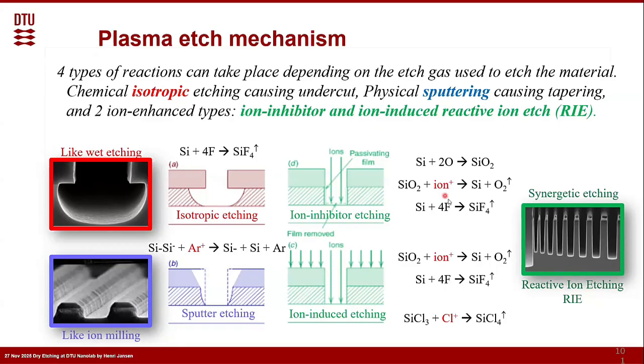And then the 2 most important ones, that is ion inhibitor and ion induced. Ion inhibitor is, in a way, still depending on the isotropic etching, in the sense that the material you want to etch is still very volatile. To prevent it from undercutting like isotropic etching, what we do, we introduce an extra gas which is inhibiting it. So it could be oxygen or fluorocarbon in some cases. Here I take the example of oxygen, because it will create silicon oxide, which is non-volatile.